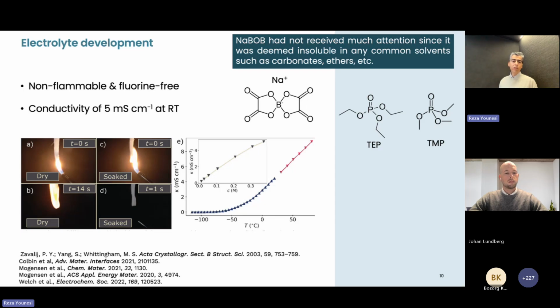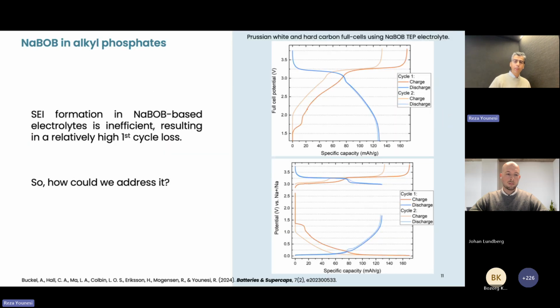You can easily achieve C/3, C/2, and even 1C in big multi-layer pouch cells, as we have demonstrated at Altris. The issue with this electrolyte, however, is that the first cycle Coulombic efficiency is low. As you see, you lose around 20% capacity on the first cycle if you use this electrolyte as it is, without any modification.